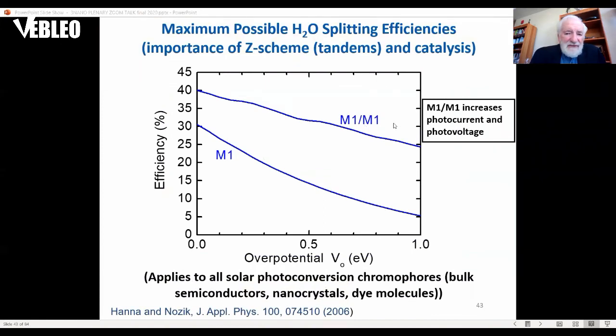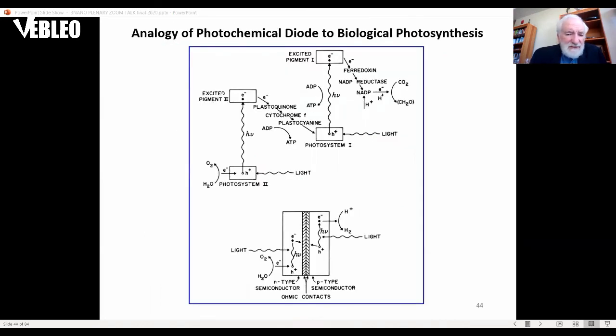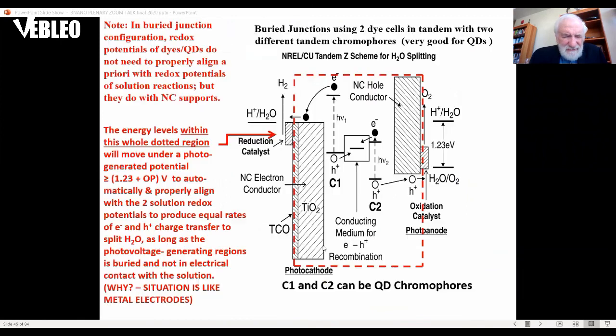And you can see if you have that, you get a much higher efficiency as a function of the overvoltage, and that's determined by how good the catalysis is at the surface where you actually do the electrochemical conversion, essentially in the dark. And it's similar to what nature does in having 2 photosystems, but in the case of the semiconductors, it's called artificial photosynthesis. It does the same thing, absorbs 2 photons, combines 1 electron and 1 hole from each of the 2 phases, but uses the high energy electron and the high energy hole, 1 each from each half of the cell, to give you the high voltage needed to split water, which ranges from a thermodynamic minimum of 1.23 volts to a realistic value of about 1.7 when you add about 0.5 volt of overvoltage, which reflects the inefficiency of the conversion.